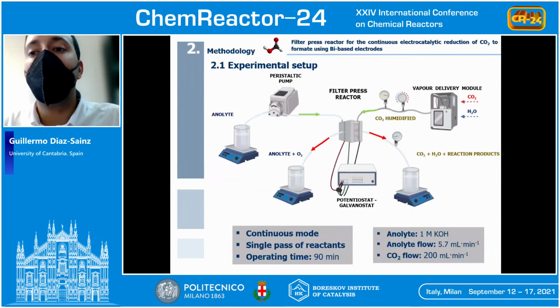The key element of the experimental setup is the filter press reactor, which is a two-compartment electrochemical reactor. On the one hand, we use an anolyte aqueous stream, a potassium hydroxide solution with a concentration of 1 molar and a constant flow rate of 5.7 milliliters per minute. On the other hand, the feed at the cathode side of the electrochemical reactor is a carbon dioxide humidified input stream using a vapor delivery module, which allows control of the flow of carbon dioxide, the flow of water, and the temperature. Finally, the current density supplied to the electrochemical reactor is given by a potentiostat-galvanostat.